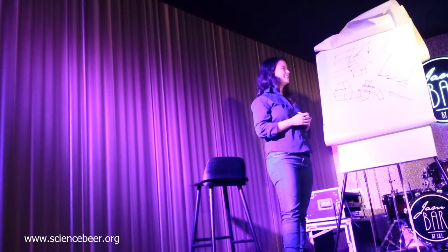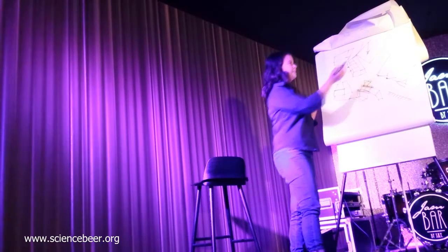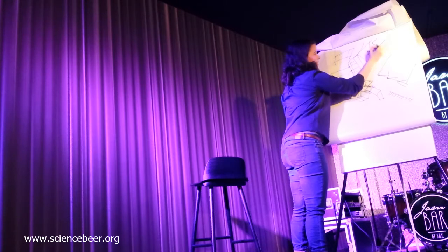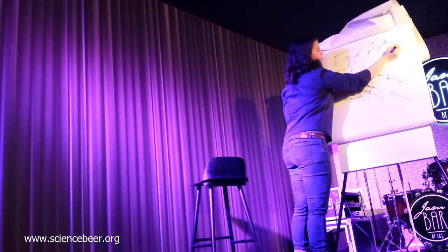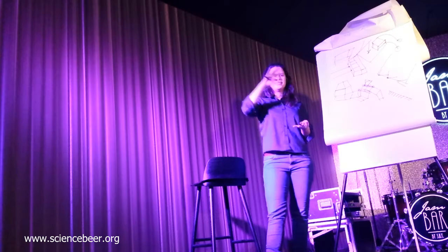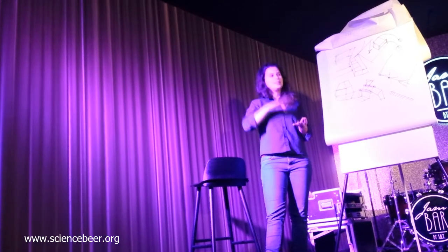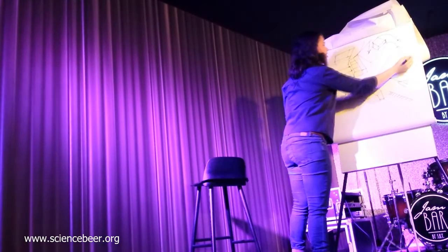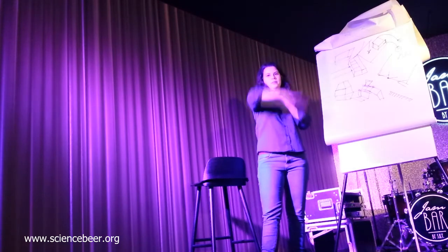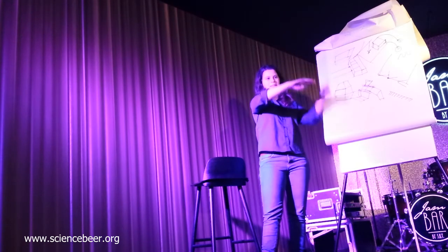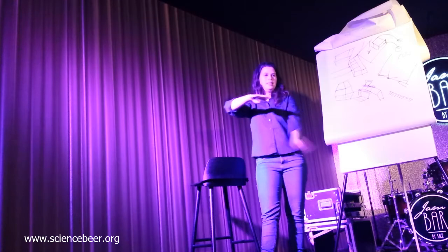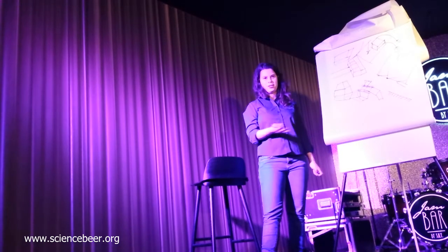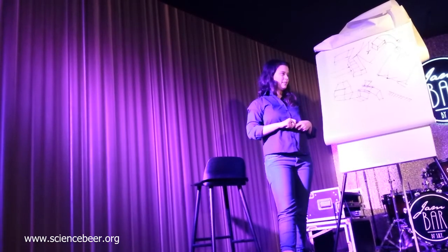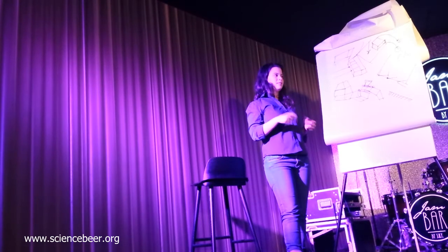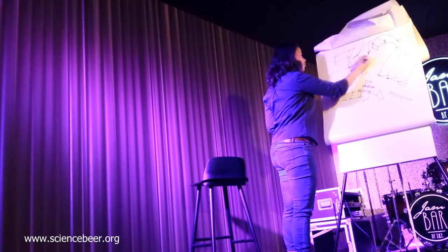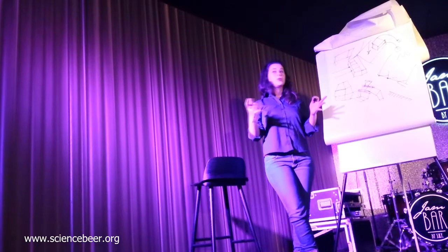What we do in order to shape this blade while it's printing is put a vibrational mechanism here. It's a tiny crystal that, when you apply voltages, it expands and contracts, and by, for example, applying an alternate voltage, we can get it to move like this, which moves our blade like this. And then our liquid is supposed to mix and form a more continuous layer. So this is my project at the moment. So far, what we wanted it to do was improved crystallization, to make these very nice smooth films and channels that would be single crystal.